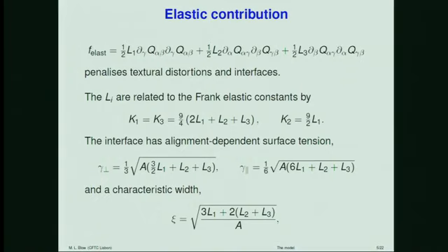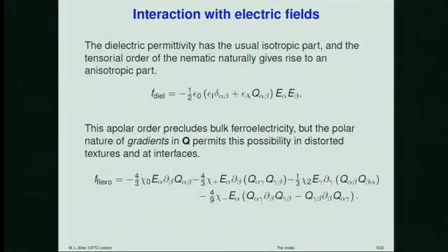And as you can see, we have different surface tensions depending on whether the orientation at the interface is perpendicular or parallel, and also the interface has a characteristic width known as the correlation length that depends on these elastic coefficients.